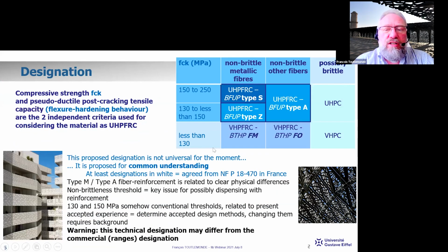For the designation of this material, we have to distinguish two key aspects. The first one will be the compressive strength. In continuity with what we do for concrete, we measure it on cylinders, and we have to distinguish thresholds of 130, 150, and 250 megapascal.